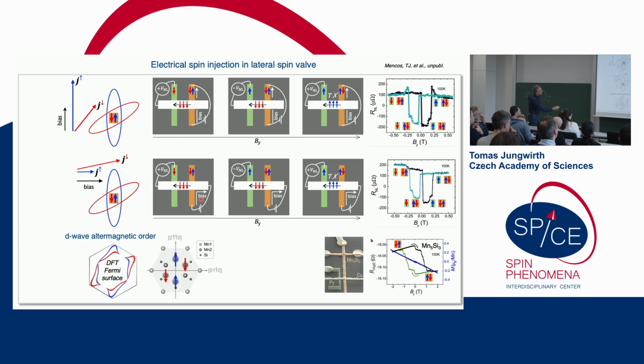So in this biasing geometry, you have a bias along, injecting into the copper channel, right? So you see you have a component of the bias which is along this direction. So for this bias, I have different numbers of spin up and spin down electrons, right? Here, when I apply the bias in the vertical direction, along the y-axis, I have no contribution from the spin up electrons, because they are all going in the vertical direction. They have no component into the copper, right? But for the red electrons, the spin down electrons, I have both a vertical but also a horizontal component, because of the tilted Fermi surface here, right? Their current is deflected from the applied bias. Here, for the blue ones, the axis of the ellipse is along the applied bias, so there's no deflection, right?